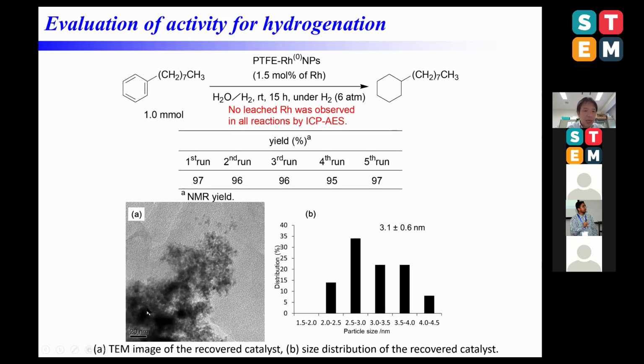However, a larger particle size and a broader size distribution were found by TEM analysis and observation of the recovered catalyst. So in this case, Ostwald ripening also occurred during the reaction.